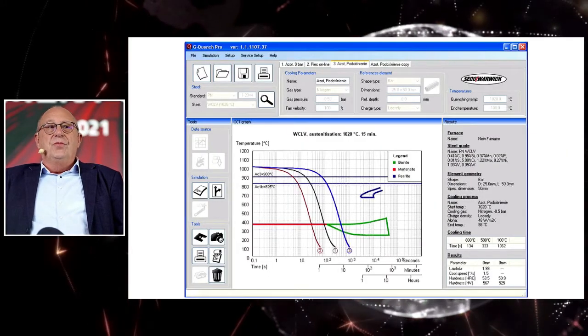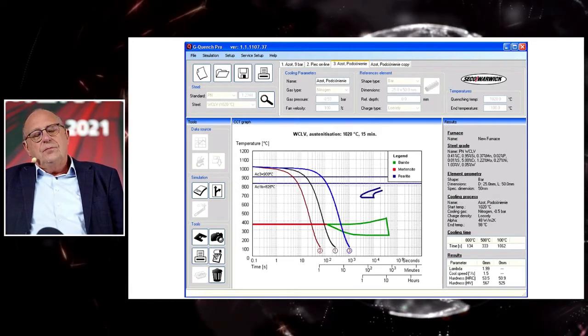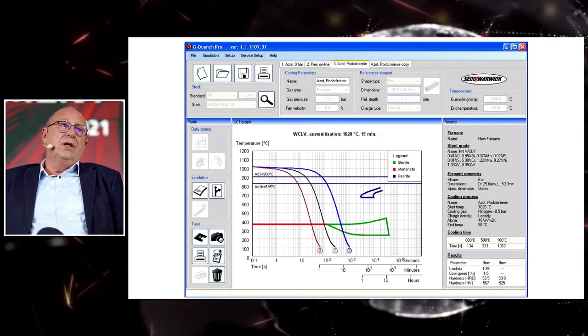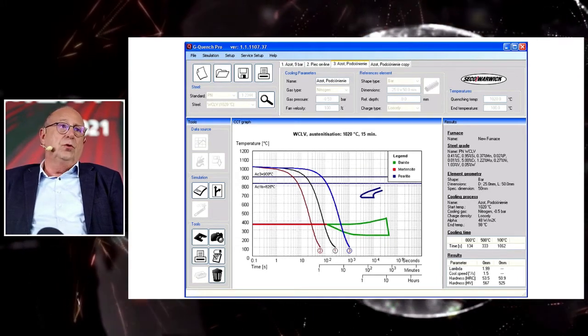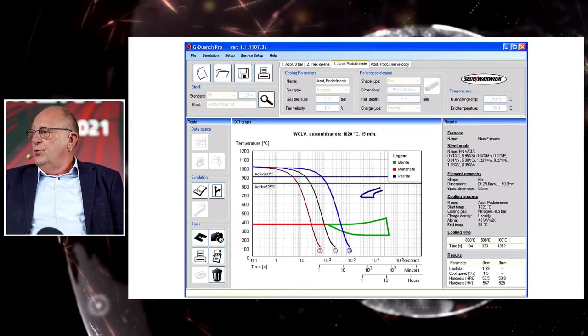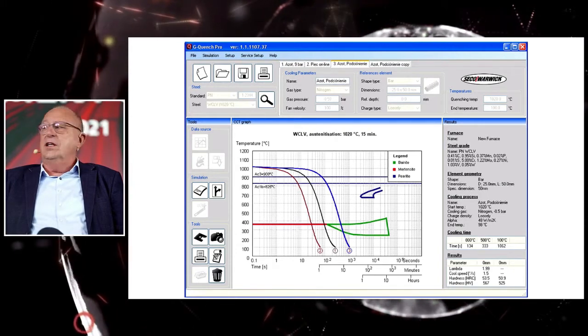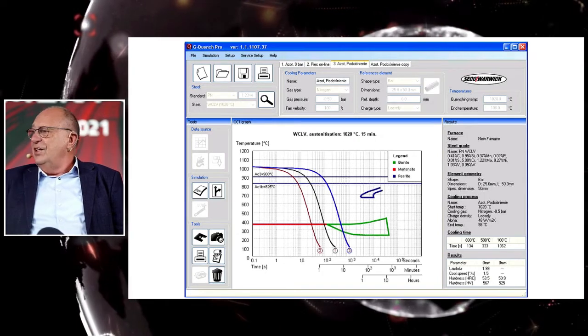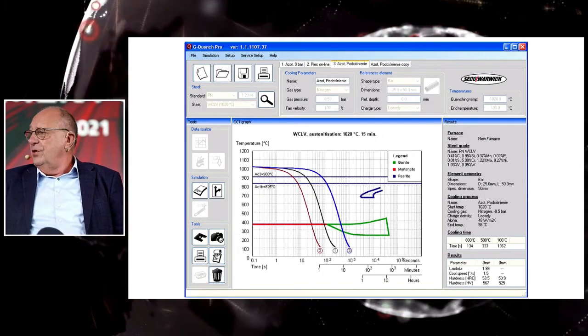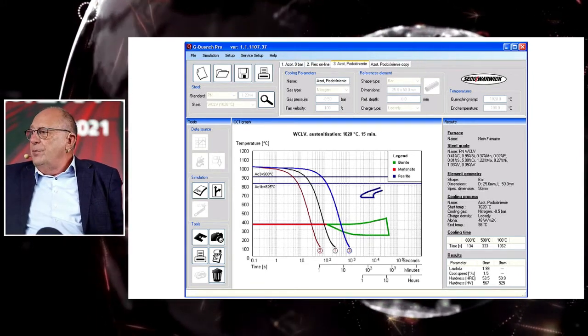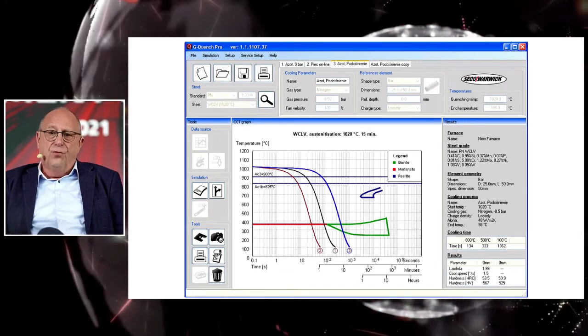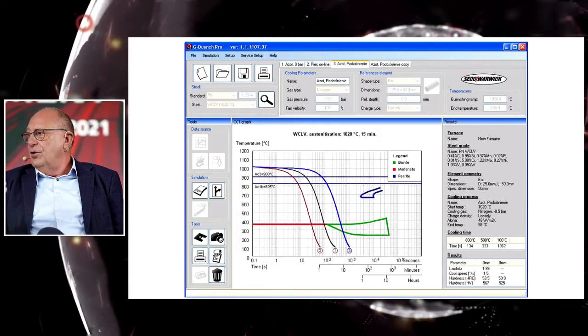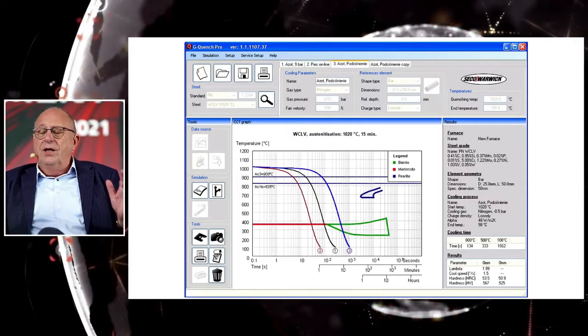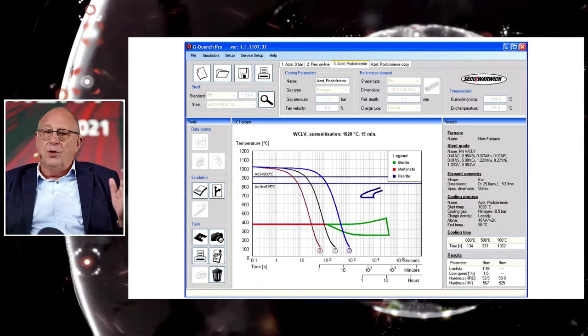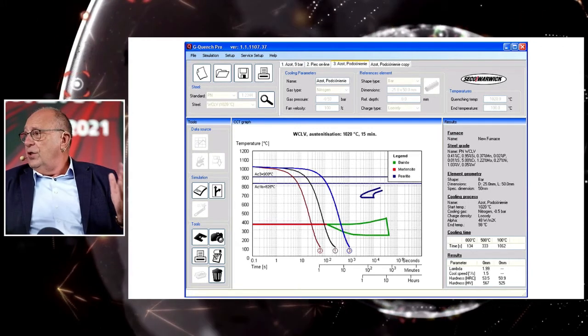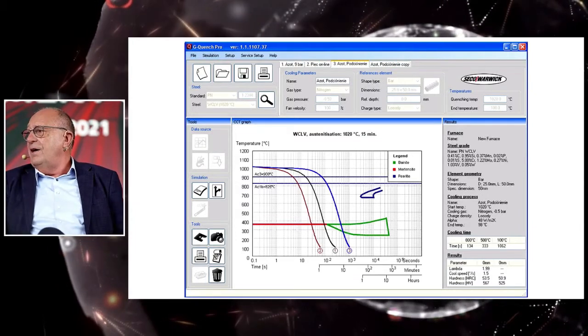So the achievements in the heat transfer efficiency enabled us to develop the next artificial intelligence tool, namely the G-Quench Pro software. This G-Quench Pro software is dedicated especially for high alloyed steels, die steels, high-speed steels, generally tool steels, and especially dedicated for the large products like dies for forging, dies for forming, for injection casting, for injection of plastic. These are really usually the very massive parts. It's hard to foresee the proper chilling rate, the cooling rate, and its effect on the final microstructure.